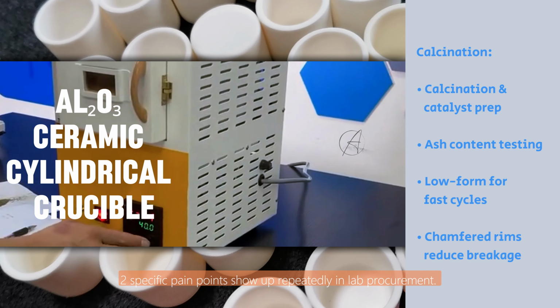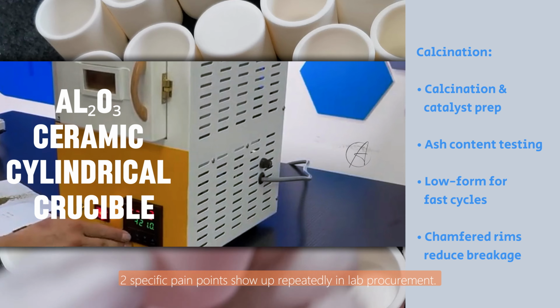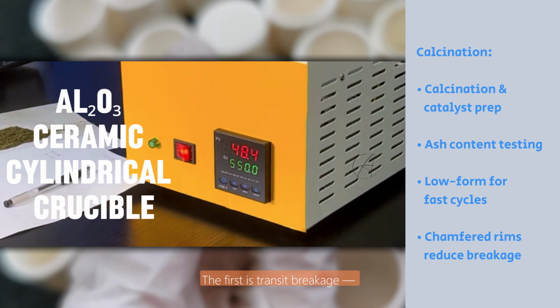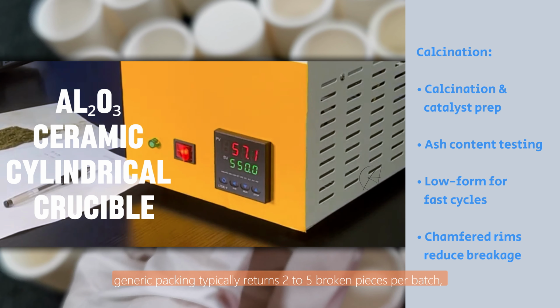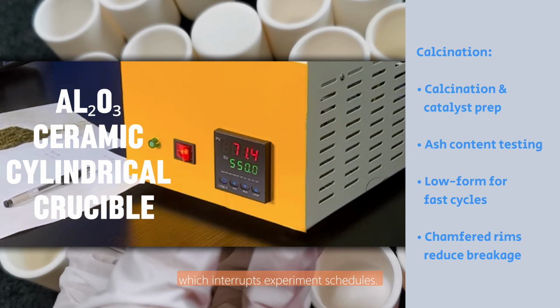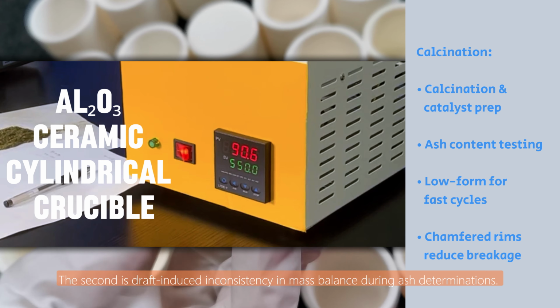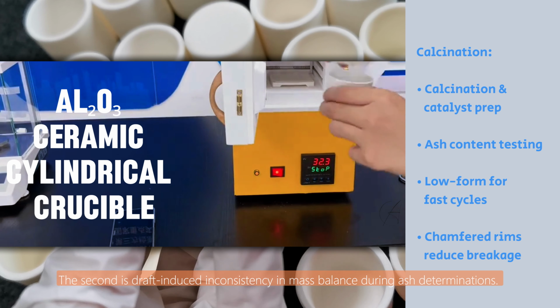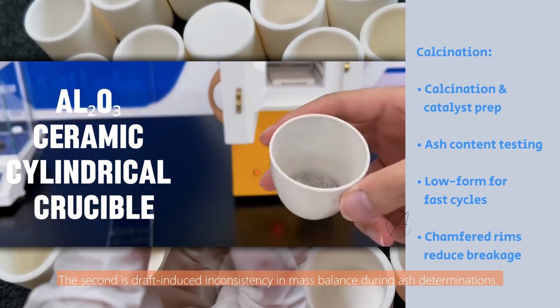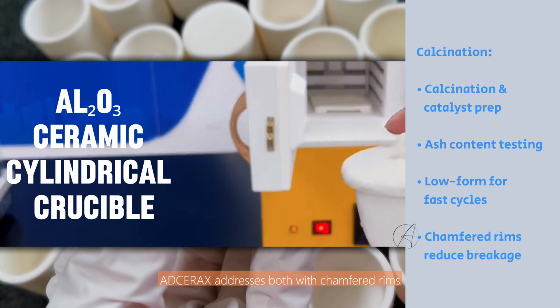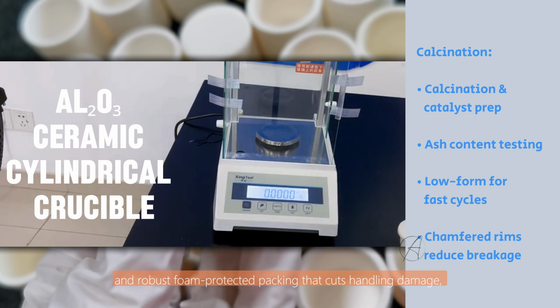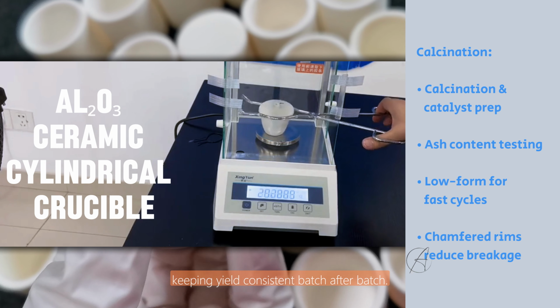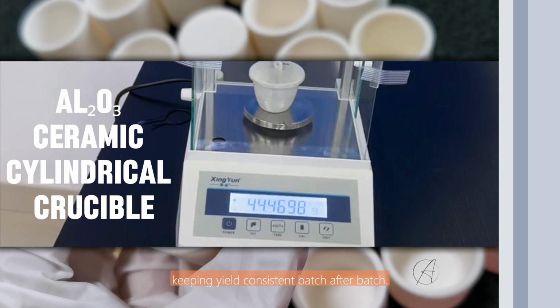Two specific pain points show up repeatedly in lab procurement. The first is transit breakage. Generic packing typically returns 2 to 5 broken pieces per batch, which interrupts experiment schedules. The second is draft-induced inconsistency in mass balance during ash determinations. ADCERAX addresses both with chamfered rims and robust foam-protected packing that cuts handling damage, keeping yield consistent batch after batch.